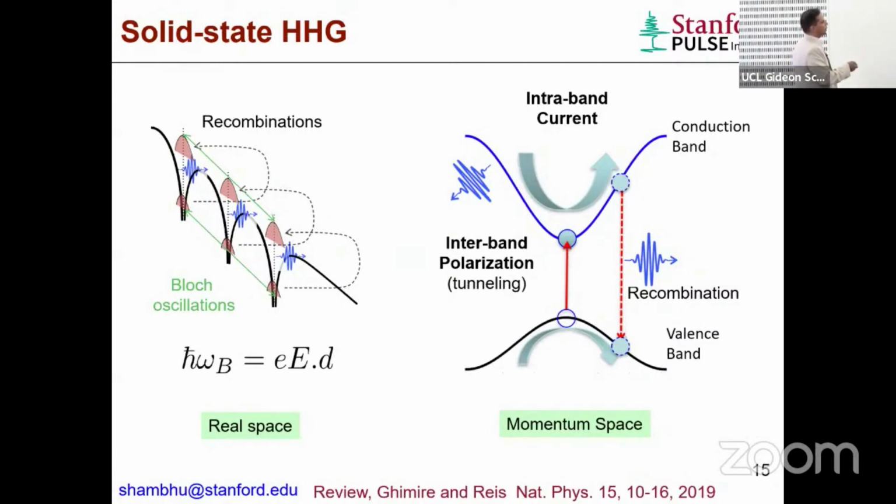This is the valence band that has some dispersion now, right? It's not flat anymore. Similarly, this is the conduction band. It's not parabolic anymore. It has some curvatures, additional components to it, which basically represent the effects from the nearest neighbors and next nearest neighbors, and depending on the type of solid, you have different types of dispersion.